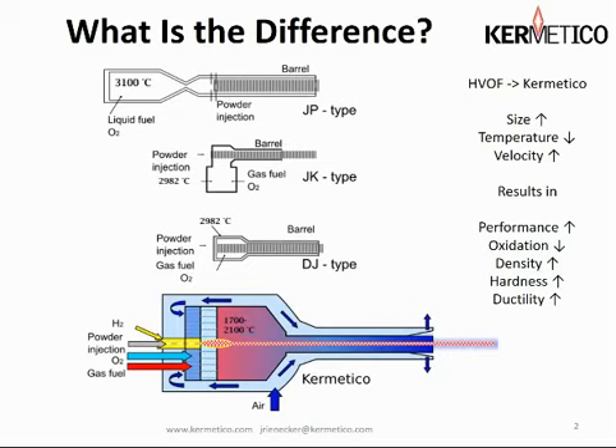Now, what we're doing here is a little bit different in that along with our powder carried with nitrogen carrier gas, we're injecting a trickle of hydrogen, not for combustion, but for thermal conductivity. Hydrogen has the highest thermal conductivity of any gas, and we use that to more efficiently transfer the heat of the combustion gases in the combustion chamber to the stream of metal passing through it. Incidentally, hydrogen acts as a wonderful oxygen scavenger to prevent oxidation of the material as well.